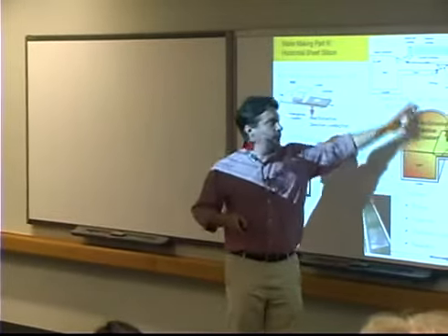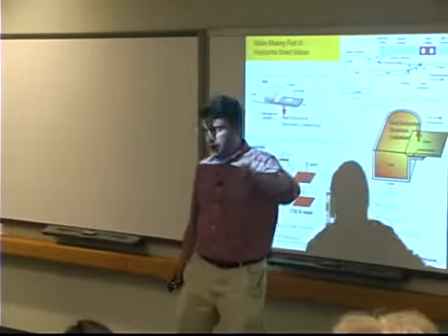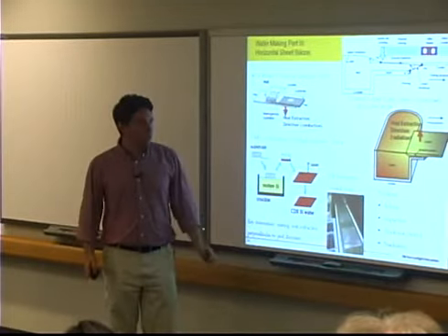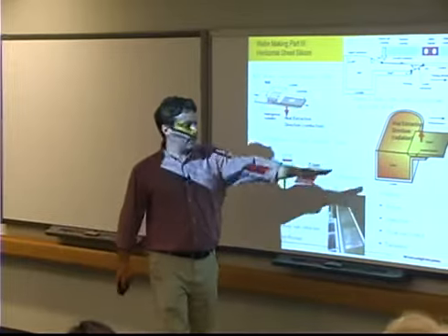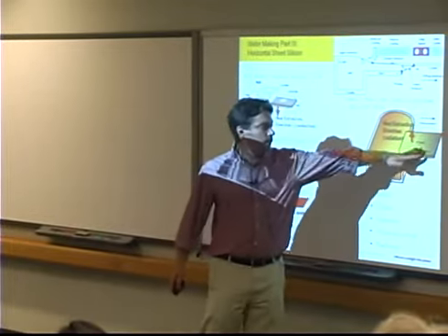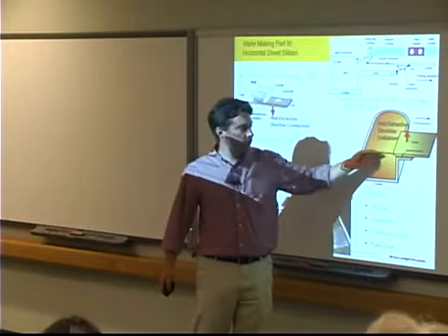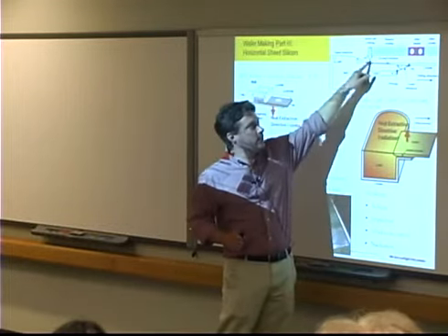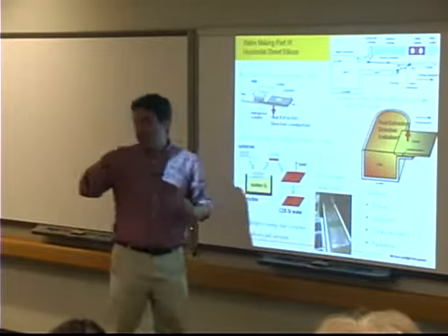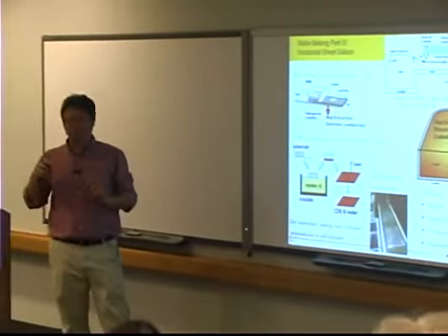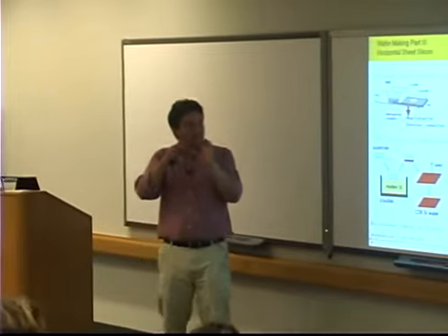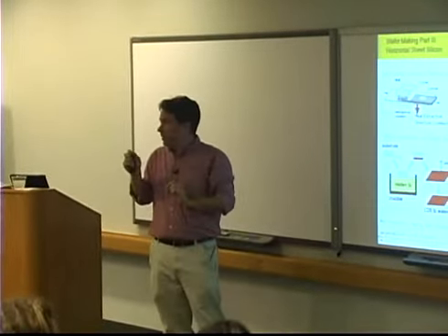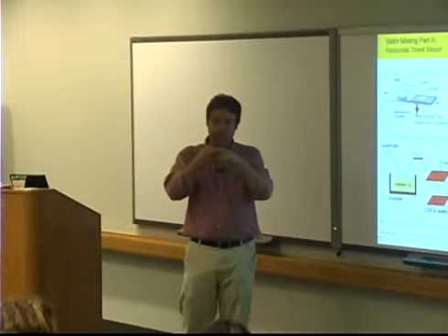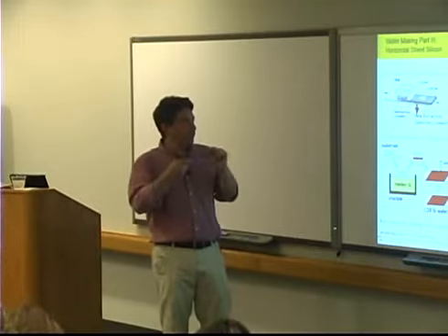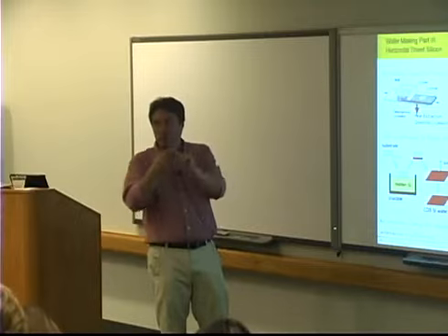So here, at least theoretically, you should be able to just pull the stuff at up to a meter per minute off the side, and since you're extracting your heat vertically, you don't have to worry about this problem we had earlier. But the tricky thing is that somewhere at the tip here, at some scale, that tip is going to have some kind of curvature to it. And at that very tip, you're going to have that same problem of your heat extraction and your growth being closer to the same.